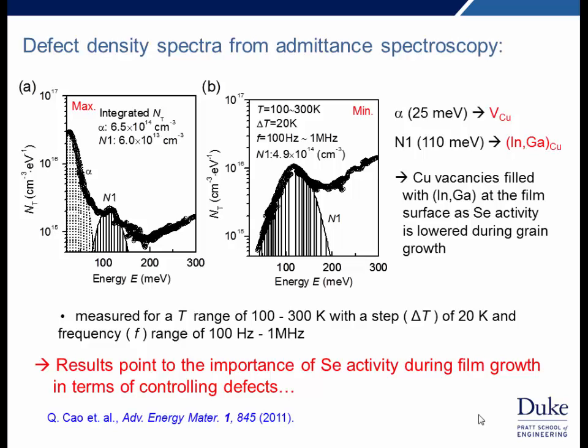And as we go from the maximum selenium activity to minimum selenium activity, we see the reduction in this alpha feature and the enhancement of this N1 feature, which is supportive of this idea that copper vacancies are being filled by gallium at the surface of the film when the selenium activity is lowered during grain growth. And so what I think is important about this is it shows the importance of controlling selenium activity and heating rate during the growth of high-performance films.